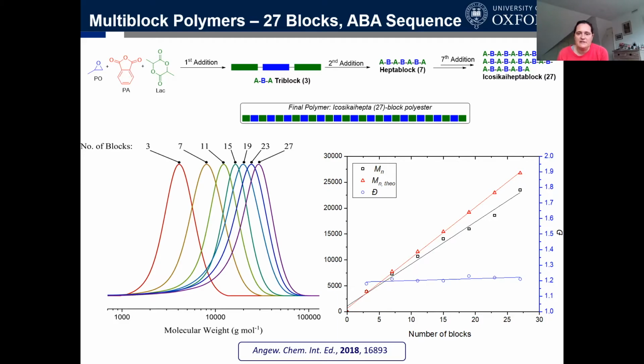And here is some data to support that finding, because you can see the GPC traces are continually evolving to higher molecular weight as Dan adds progressively more monomer mixture into his catalyst staying alive throughout the reaction, and the molecular weight of the polymer increasing linearly with the number of blocks added, and the dispersity staying really narrow, so fully consistent with high polymerization control.